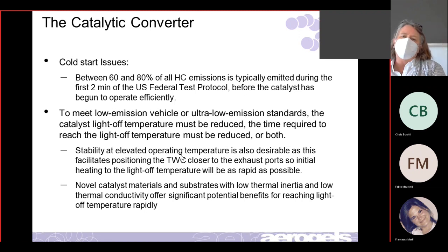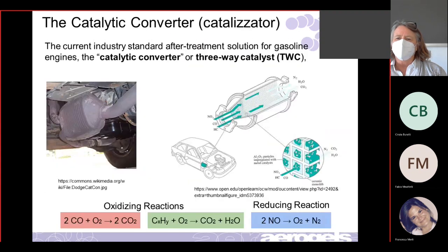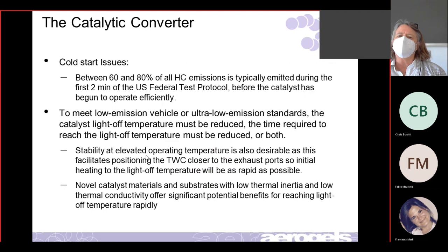So you want a material that's stable at high temperatures, because if you have something stable at high temperatures, you could conceivably, so here's my engine and here's my catalytic converter, move it closer to the engine, because if it can take high temperature, that would be good. So something that's stable at high temperature would allow you to position the three-way catalyst closer. And then if it's closer, it's going to heat up faster. And the other thing is, if we could make materials with low thermal inertia, or low mass, they don't weigh much, they'll heat up faster. So that's another thing where new materials could help out.